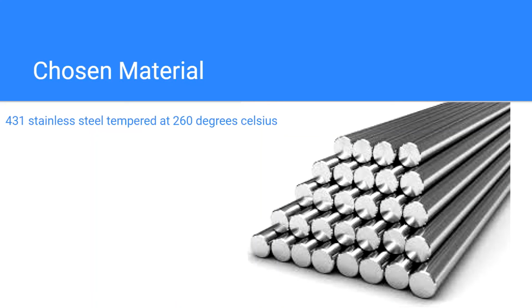Most of the materials that met the requirements were low alloying steels like 1030, 4140, and 5160. Several stainless steels also met the requirements. Since the goal was to pick a material that would perform better than the existing bolt in the stanchion between E3 and DC, a stainless steel bolt was chosen as the substitute so that it would have better resistance to corrosion, which is a functional requirement. Since all remaining materials met the requirements, the cheapest stainless steel that was rated as not susceptible to galling or stress corrosion was chosen, which was 431 stainless steel, tempered at 260 degrees Celsius.